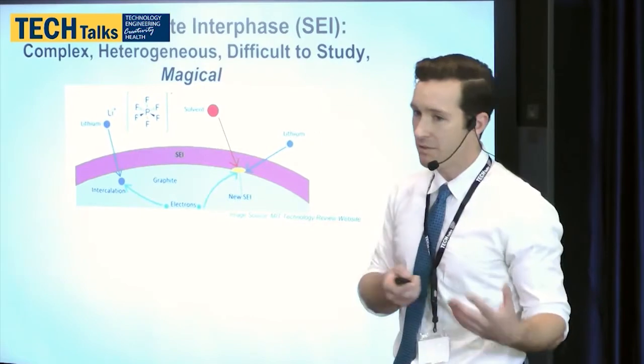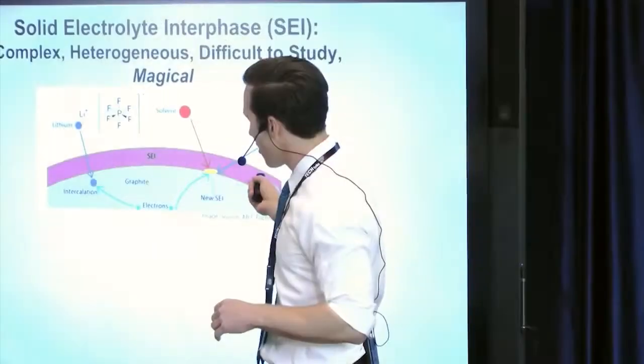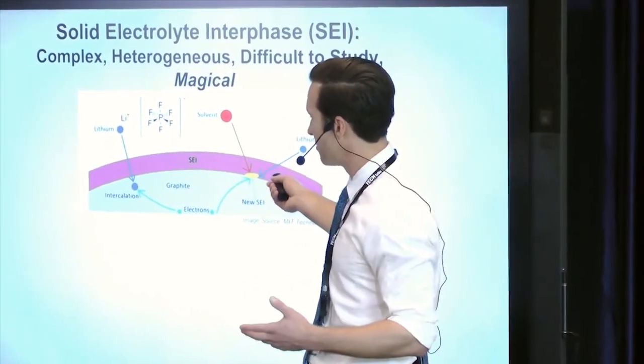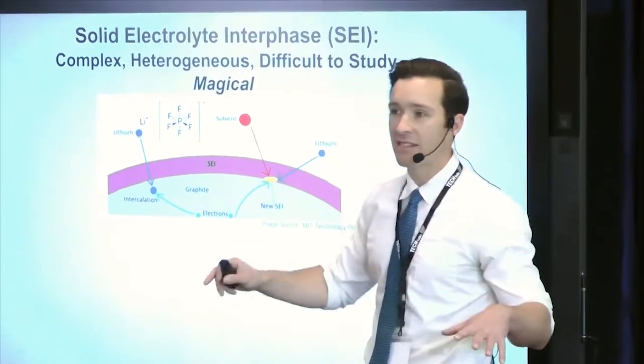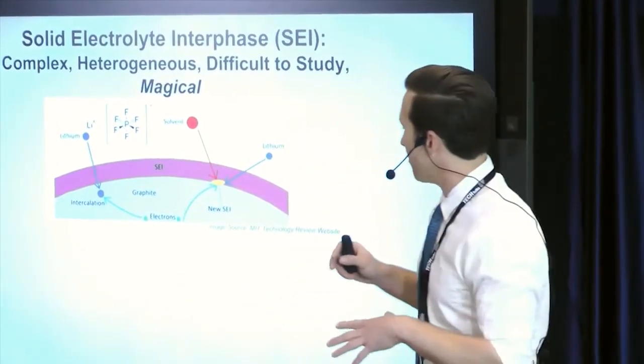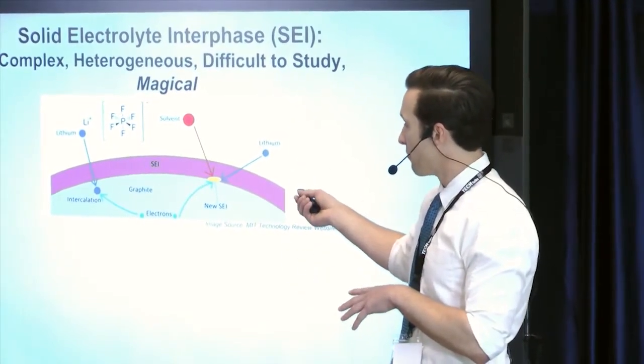The electrolyte is simply not stable over the voltage range of 0 to 4.3, and it undergoes reductive decomposition at the anode at the low voltage. So, on the first charge with graphite, you develop this SEI layer through decomposition of the electrolyte, but it's a self-passivating film. It's like aluminum oxide on aluminum. In a well-functioning battery, it prevents further solvent reduction.